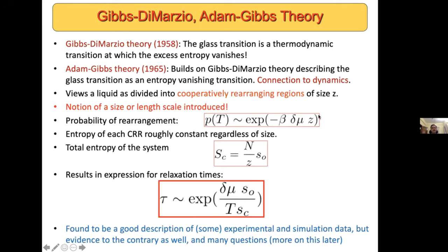And if one puts these two equations together and writes an expression for typical relaxation times, one gets the Adam-Gibbs relation, which says the relaxation times go exponentially as 1 over the configurational entropy. And since the configurational entropy is vanishing as one approaches the ideal glass transition, this would correspond then to a divergence of the relaxation time. But more specifically, it's a very strong divergence of the relaxation time, because if for the sake of simplicity, one says that TSC goes as some T minus T naught, where T naught is the glass transition temperature, you have an exponential 1 over T minus T0 dependence, which is a very strong dependence. And that's indeed the Vogel-Fulcher-Tammann dependence that one does fit a lot of experimental data to.